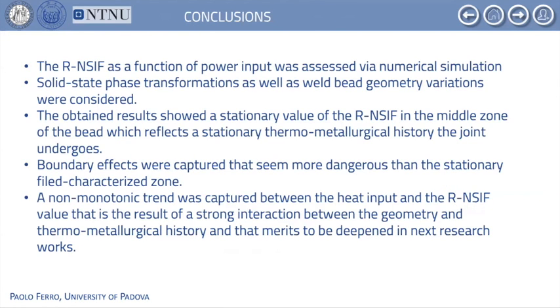So, we came to the conclusions. The residual notch stress intensity factor as a function of power input was assessed via numerical simulation. Solid state phase transformation as well as weld bead geometry variation were considered. The obtained results showed a stationary value of the residual notch stress intensity factor in the middle zone of the bead, which reflects the stationary thermometallurgical history the joint undergoes. Boundary effects were captured as well, which seem more dangerous than the stationary field zone.